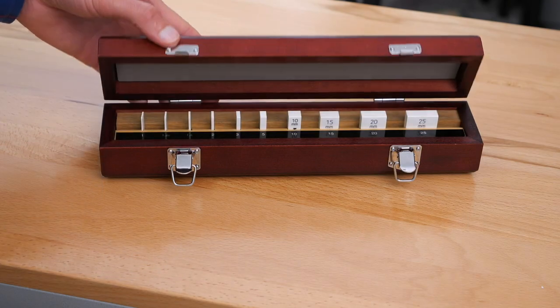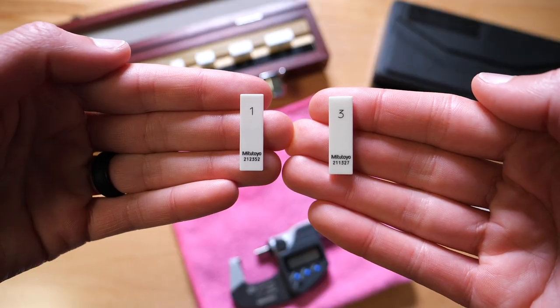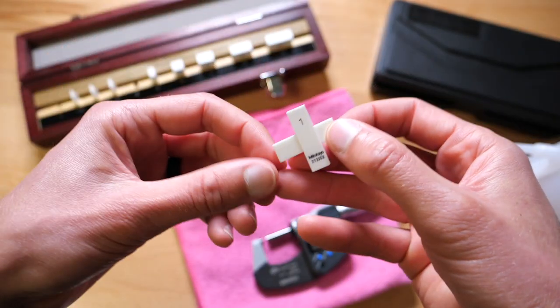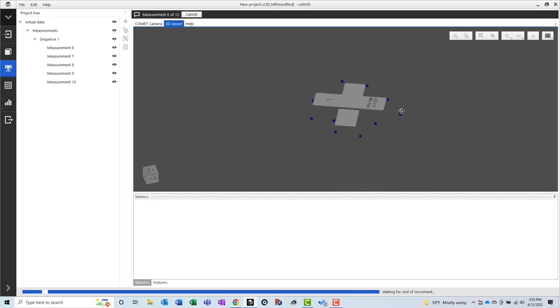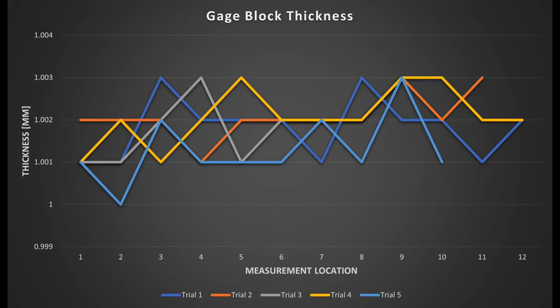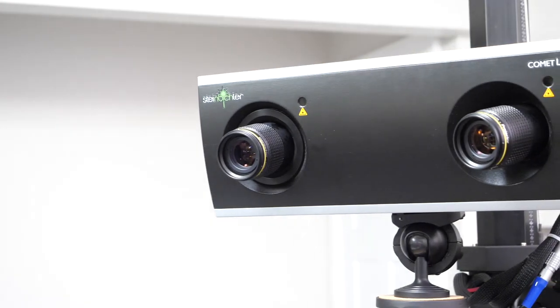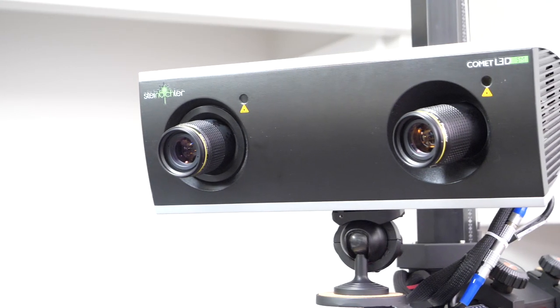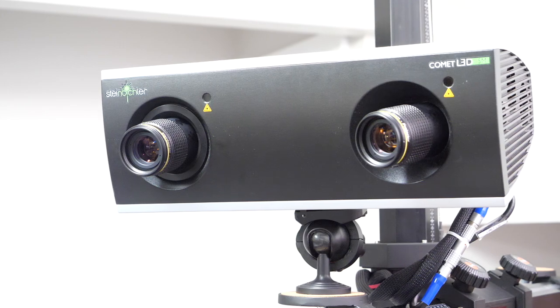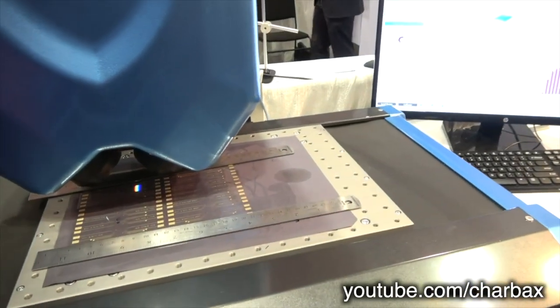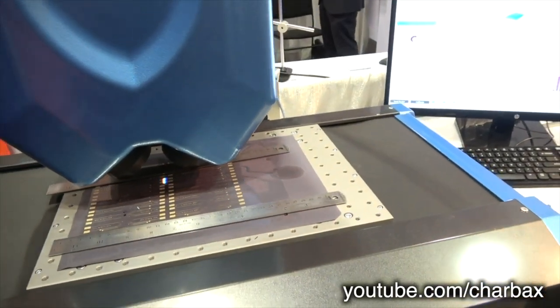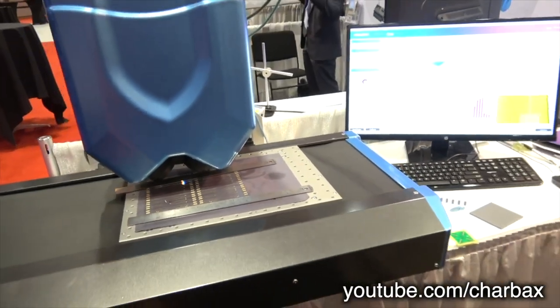Now, in order to make sure my scanner can detect a tiny change in thickness, I first scanned two wrung together grade zero gauge blocks several times. I then measured the thickness of the top gauge block on each scanned mesh. The thickness measured was repeatable to about two or three microns, so my Steinbichler Comet L3D scanner should be able to handle these tests, but just barely. I'd rather use a non-contact surface profilometer to check thickness and roughness, but since I don't have one, my scanner will have to do.